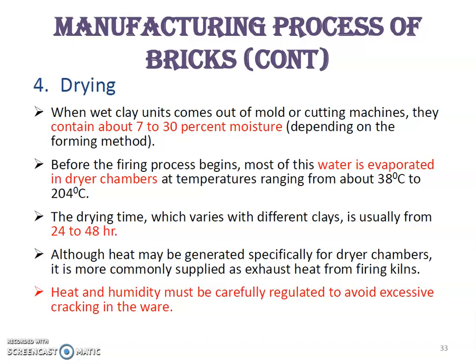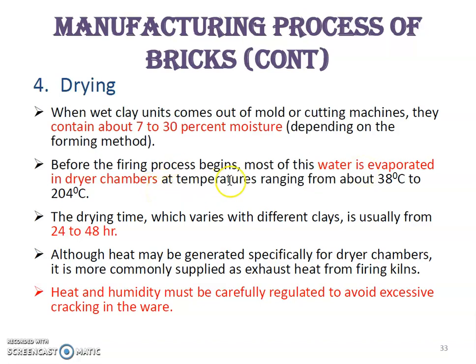The fourth process is drying. When wet clay units come out of the mold or cutting machine, they contain 7 to 30% moisture, depending on the forming method. Before the firing process begins, most of this water is evaporated in a drying chamber. The temperature in the drying chamber is about 38°C to 204°C.